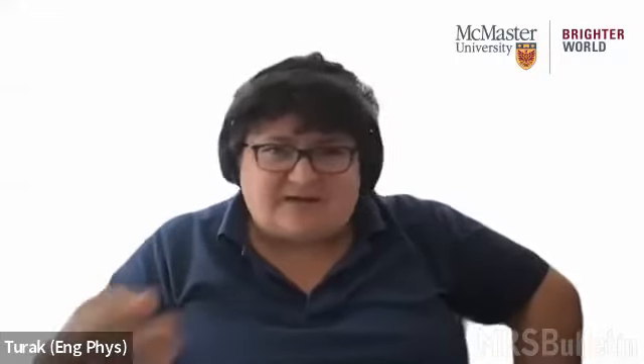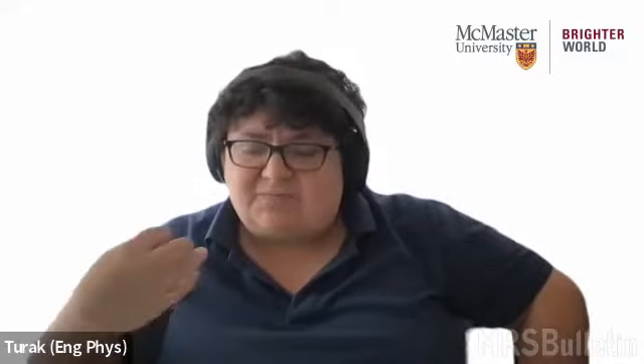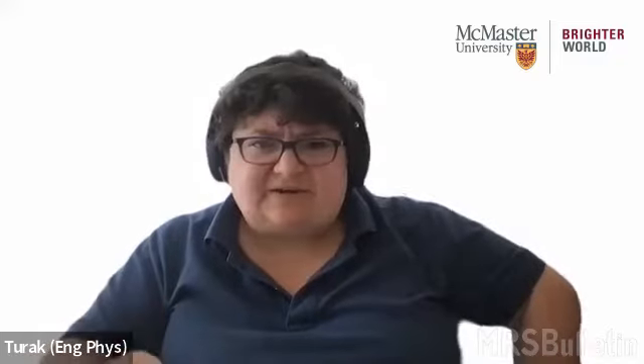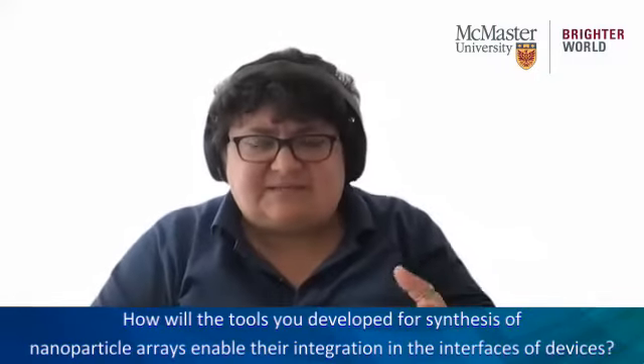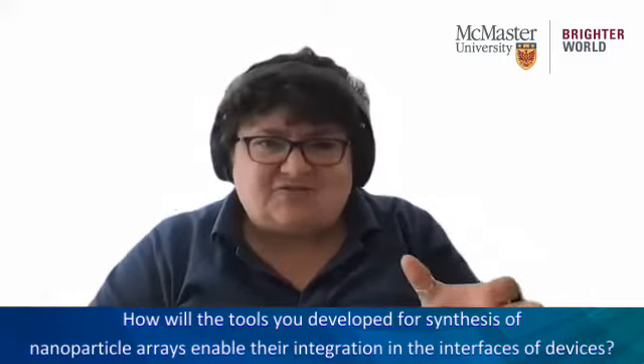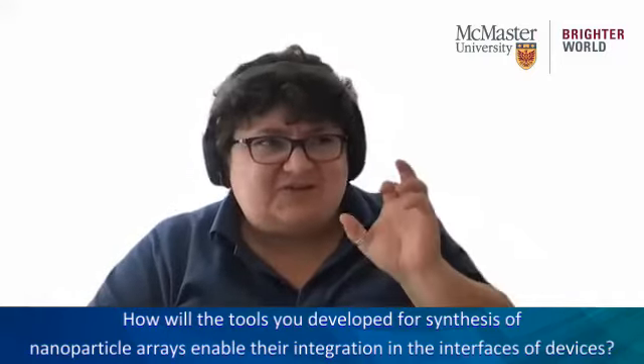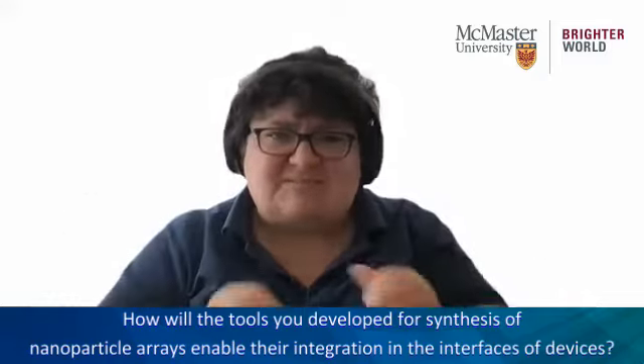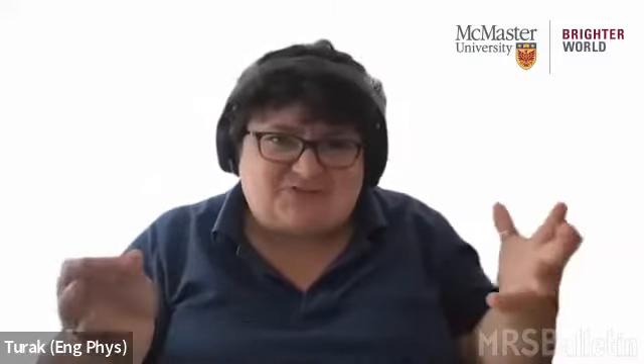Absolutely. So just to expand on what I was saying a little bit earlier, the approach that we've taken is based on forming a reverse micelle in solution, and a reverse micelle is basically a polymer material that has one hydrophilic and one hydrophobic end. So when you put it into a solvent, it immediately forms this macromolecule that we call a micelle. And everybody would be familiar with micelles because that's what soap is, right? So soap basically surrounds a piece of dirt when you put it, let's say, on your plate. The polymer in a soap surfactant will just surround this material and pull it into